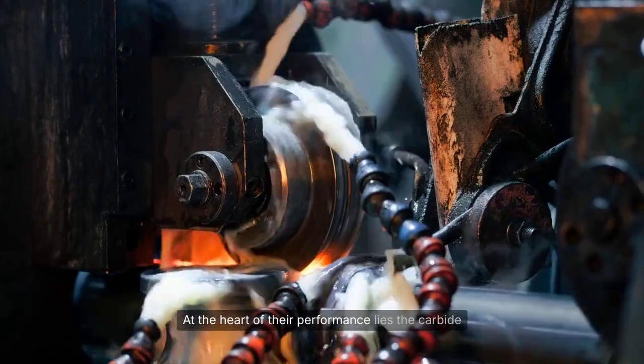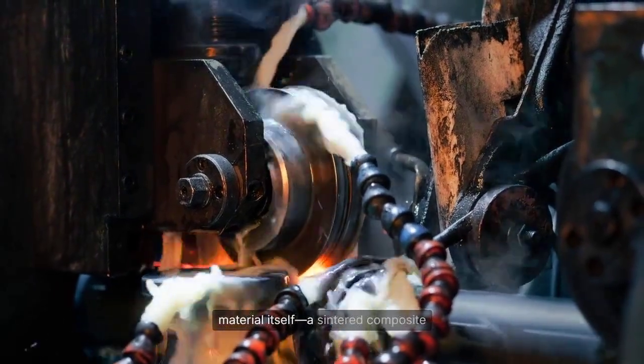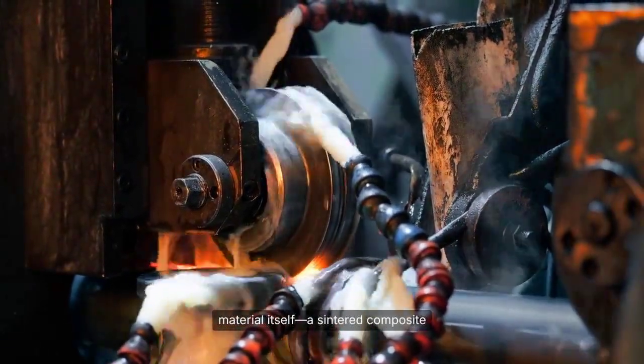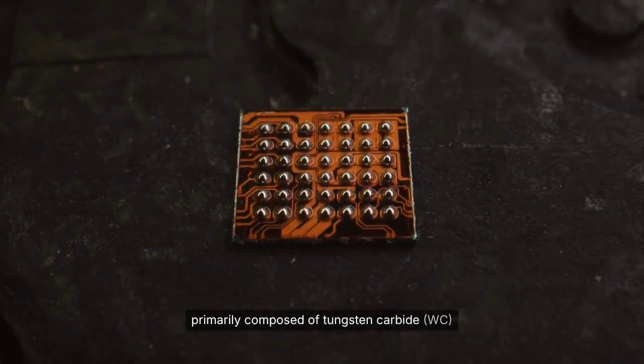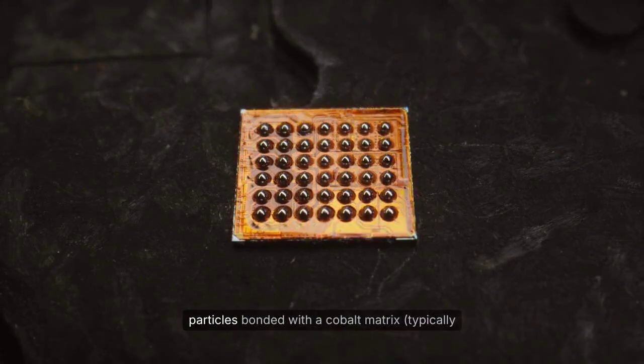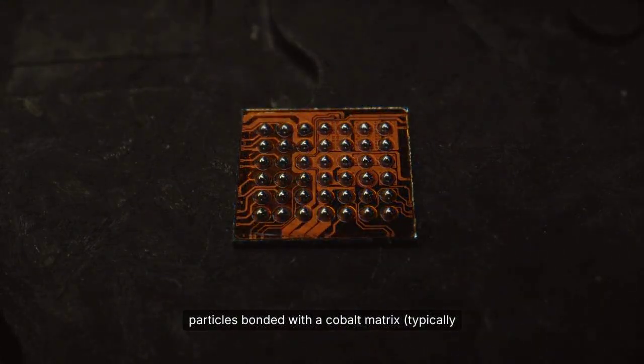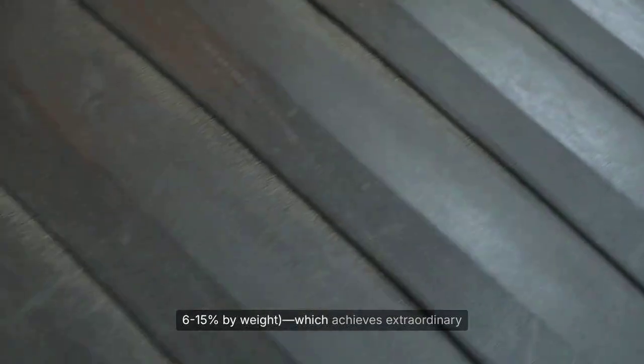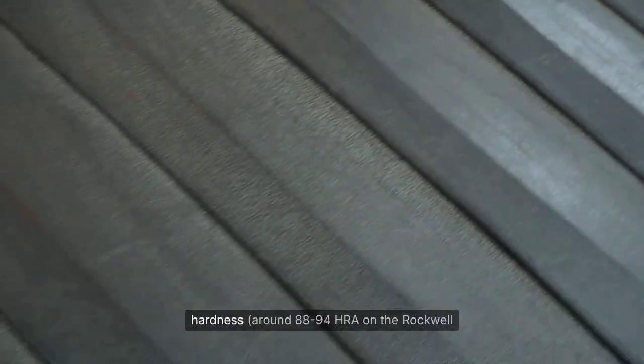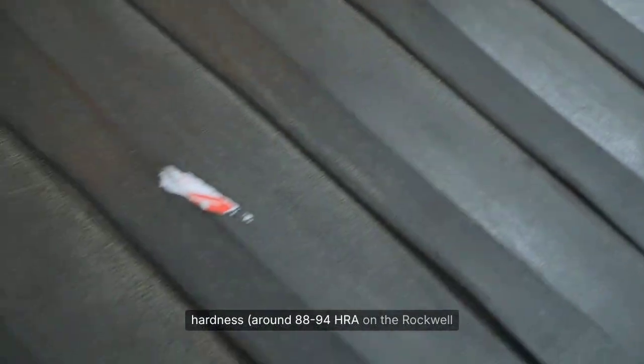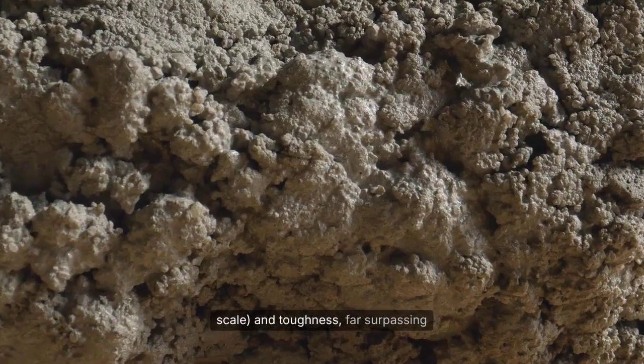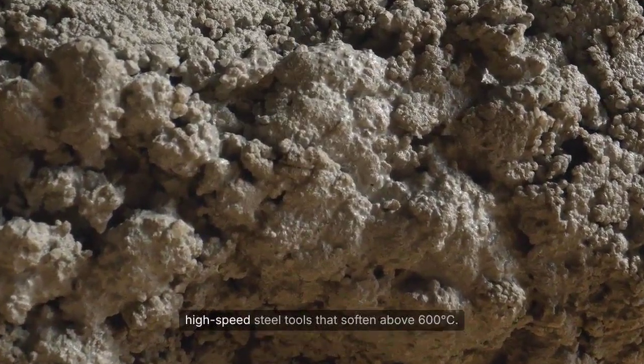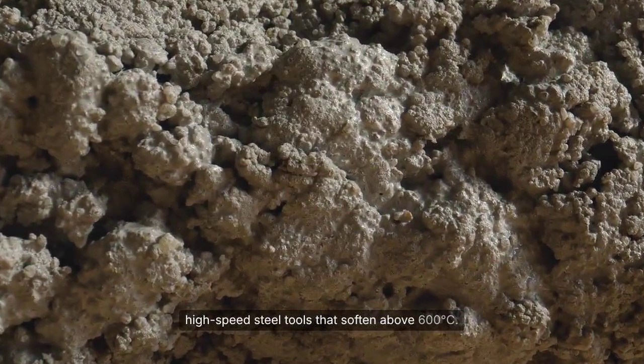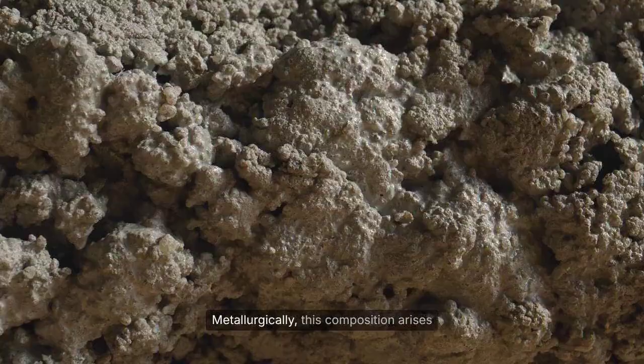At the heart of their performance lies the carbide material itself, a sintered composite primarily composed of tungsten carbide, WC, particles bonded with a cobalt matrix, typically 6 to 15% by weight, which achieves extraordinary hardness, around 88 to 94 HRA on the Rockwell scale, and toughness, far surpassing high-speed steel tools that soften above 600 degrees Celsius.